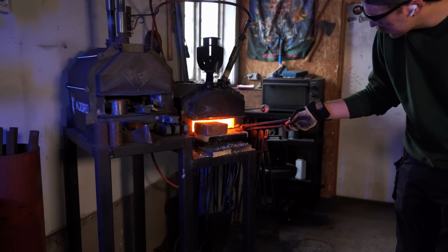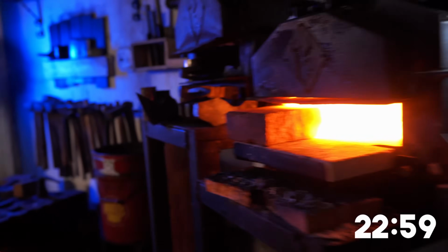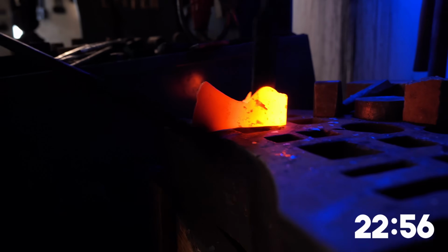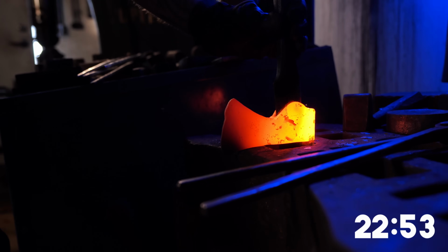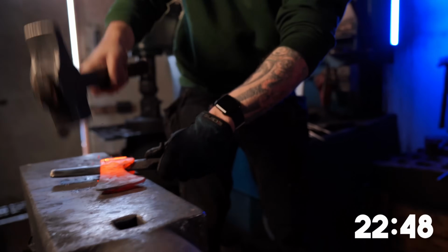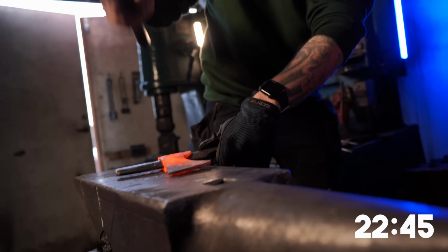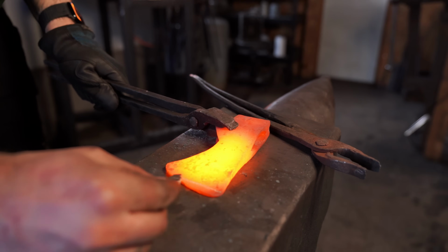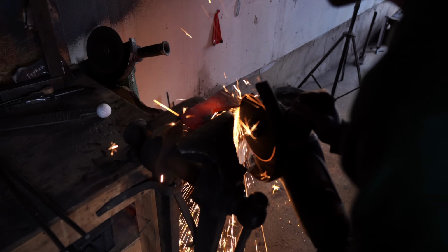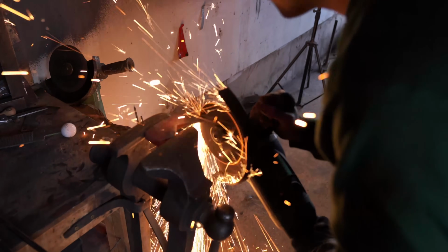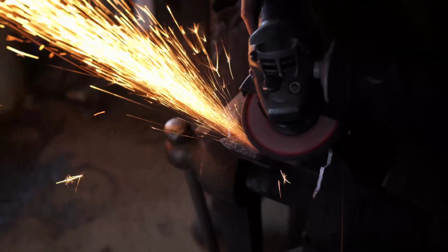Once I'm happy, well, not happy, but happy enough with the blade, I go back to the final drifting of the eye, just to make sure the eye is properly shaped and that the axe is reasonably straight. I mark out the profile of the edge using a soapstone pen and then remove some of the excess material with my angle grinder. I then go to town roughing in the edge with a flat disc on my small angle grinder.